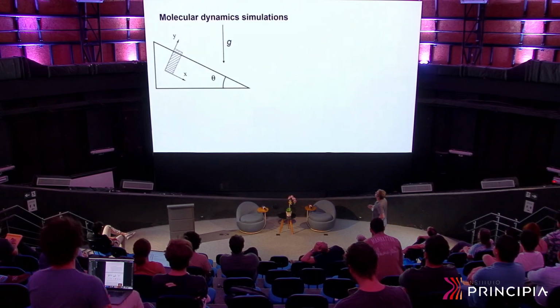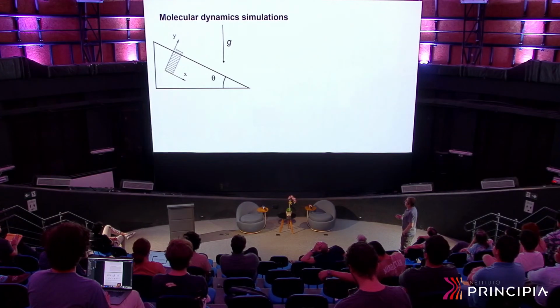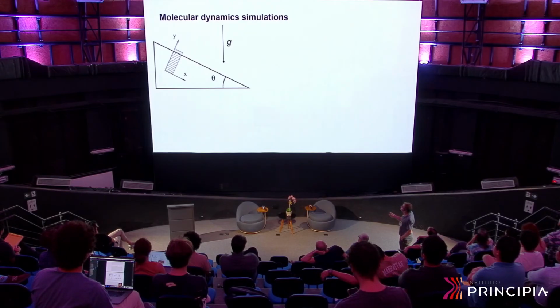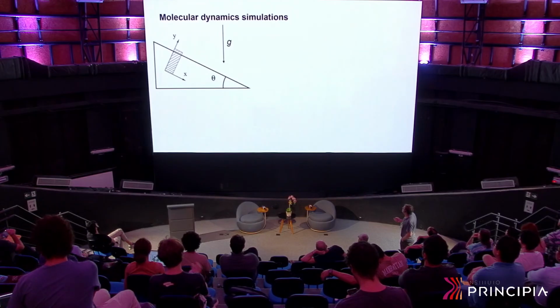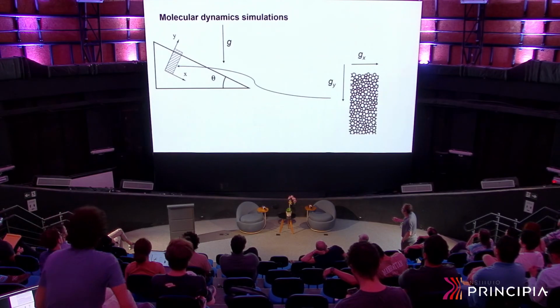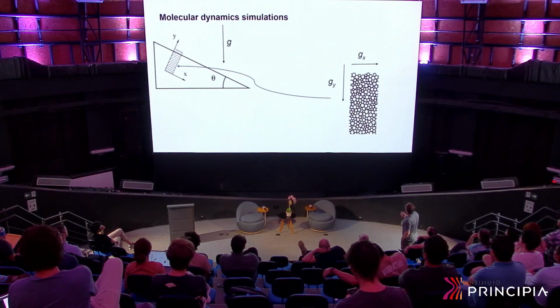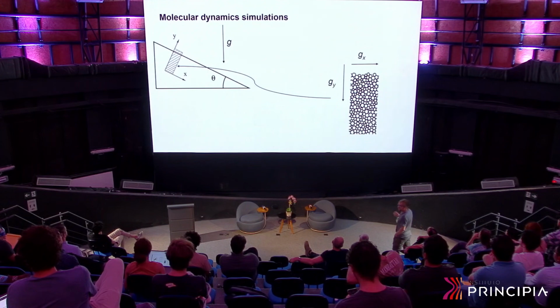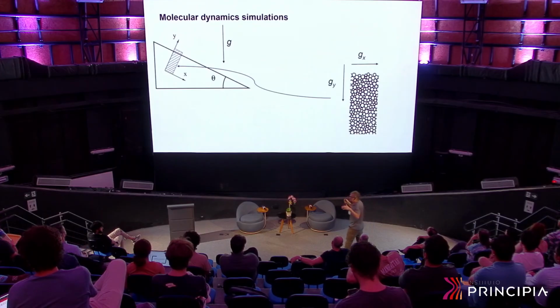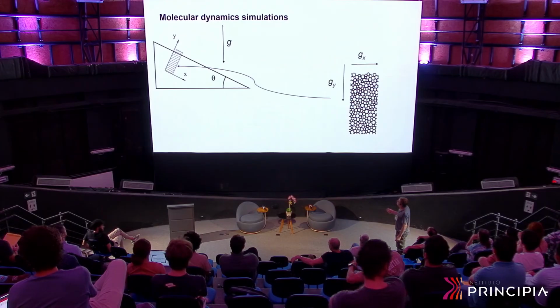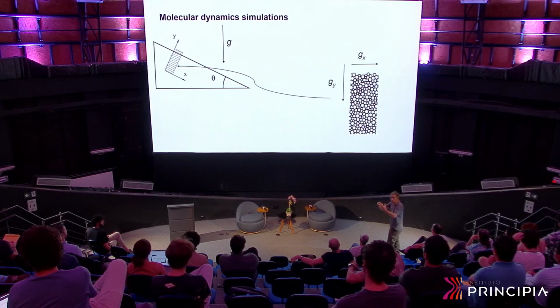To start with a molecular dynamic simulation, what we did is to consider a granular material, essentially describing the material that is contained in this rectangle, which is a piece of the material that is supposed to creep down the inclined plane. We do a two-dimensional simulation of this. We model it as a collection of disks of different radius. I will not go into many details, but these disks are frictionless, just for simplicity, but essentially they can stay at rest at some inclination of this angle because of the interlocking of the grains.